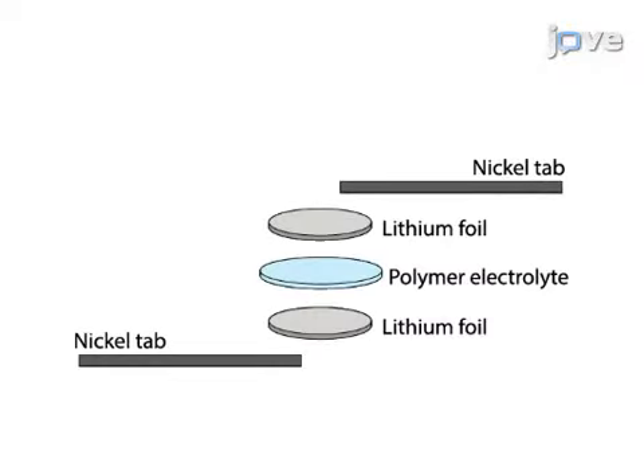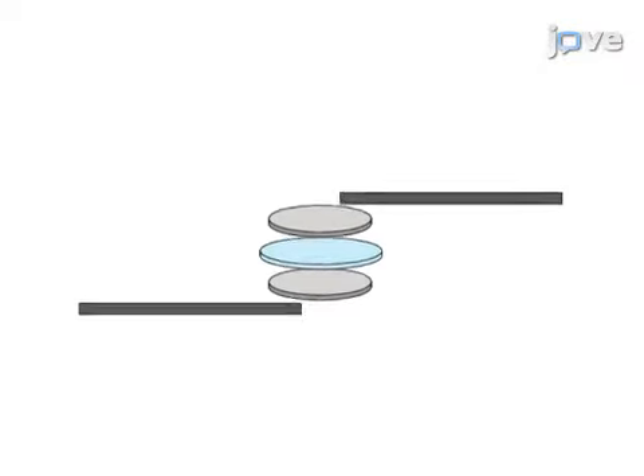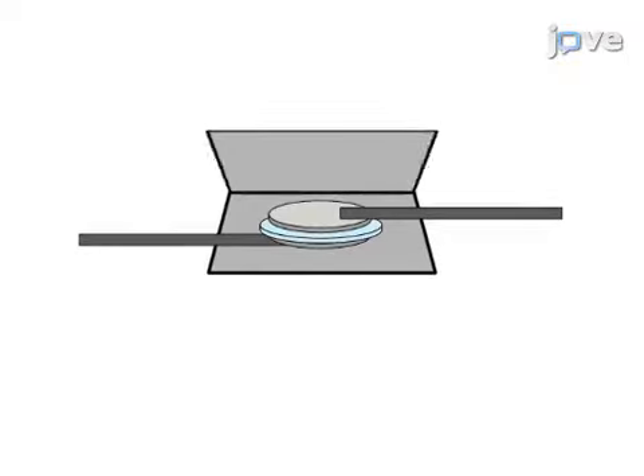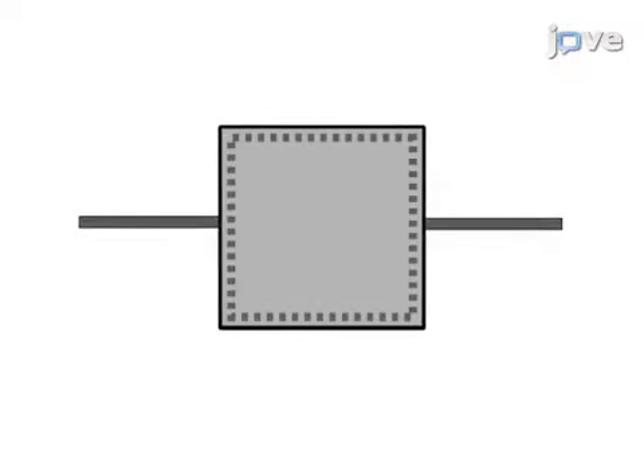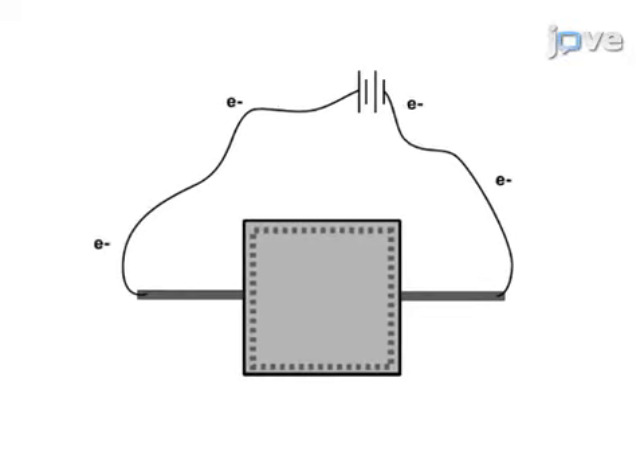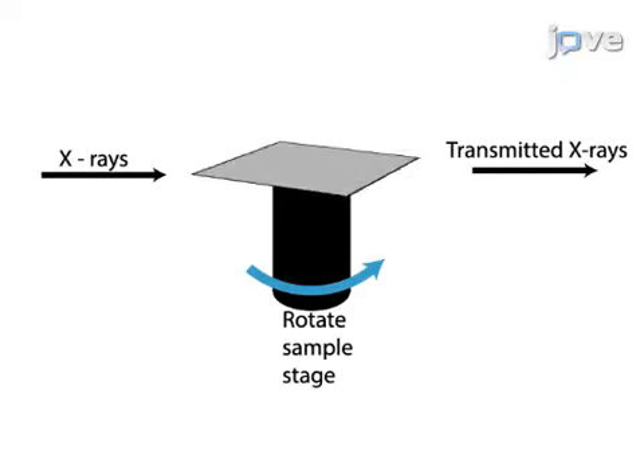The second step is to assemble the samples by sandwiching a piece of the polymer electrolyte between two lithium metal electrodes and vacuum sealing in an airtight pouch. Next, the samples are galvanostatically cycled until they fail by short circuit, or as long as desired. The final step is to reduce the sample size, remove the nickel tabs, and then image by hard X-ray microtomography.